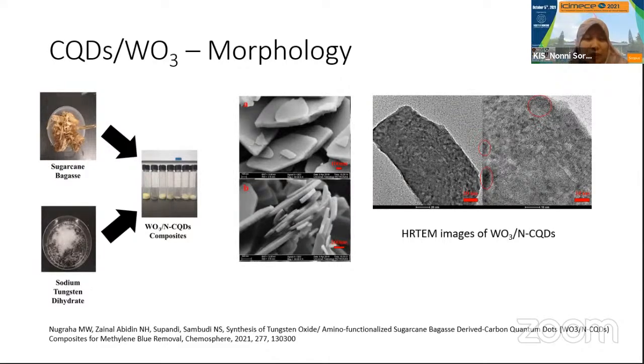Okay, so this time we want to use doped carbon quantum dots. Previously we doped with nitrogen. From that doping result, we want to combine it with the tungsten oxide. This time we have a different source that we use to synthesize the carbon quantum dots. So we use the sugarcane bagasse. Previously we used the rice husk, now we use the sugarcane bagasse. And this image over here, the one that shows layer structure, is the tungsten oxide. So the nitrogen-doped carbon quantum dot is expected to be available on the surface of the tungsten oxide, so it decorates the tungsten oxide, which is the same modification or the same structure as what we have with the titania, the combination of carbon quantum dots with titania.